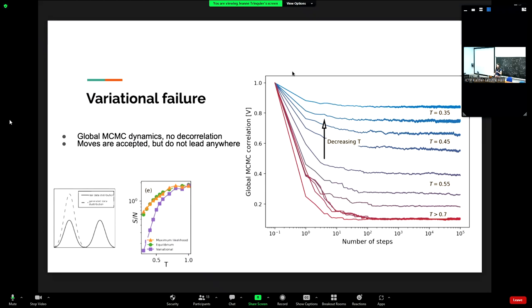So maybe you can think we are not able to explore the landscape, but at least we are able to sample some configurations, in a very small portion of the landscape, that give us some equilibrium configurations. But actually, this temperature is way higher than the critical temperature, and when we tried to decrease the temperature, it was not even able to reproduce the energy. So this is mode collapsing, and it cannot sample good configurations at a low temperature.